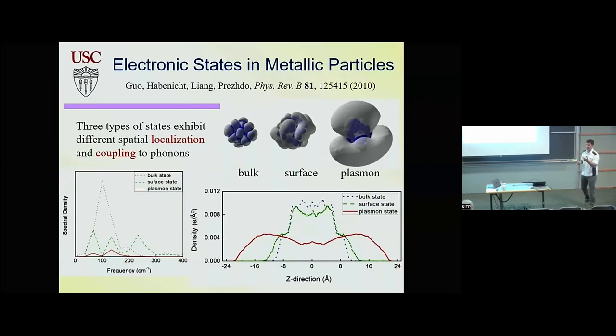And these states exist in other systems too, in semiconductor clusters too, but in those clusters, they happen at energies that are too high. That's not relevant. But what's important in this state, which is also important for transport, as I'll show you, is that it's very delocalized, and it does not couple to phonons very much. So you have this electronic state, many of them, at sufficiently high energy. For metallic particles, they're at the visible energy of plasmon resonance. And this state extends maybe a nanometer into vacuum.